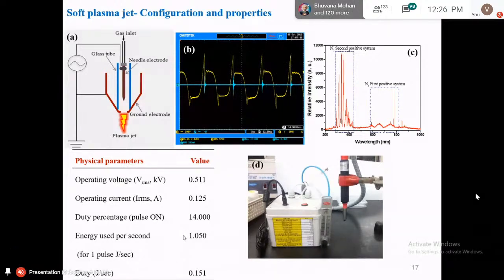In this condition, we give only a nominal voltage. It is not a very high voltage. It is around 500 volts we are applying, and the current value is 0.125 ampere. And then, we cannot continuously give the power because it will heat up this electrode, and then this glass tube will get damaged. So it should be operated in a pulse mode.